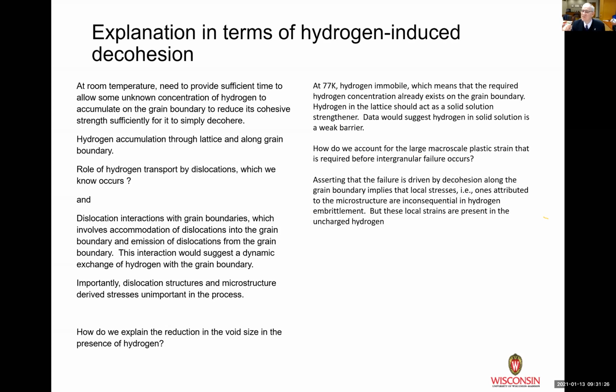The other thing I said is that it's very, very important for you to say, let me look at all of the results that are available and see if my mechanism holds up. So one of the things I showed you earlier was that at 77 Kelvin, you get a significant reduction in the ductility. You get a change in failure mode. Now, if we're really working at 77 Kelvin, we know that hydrogen is going to be trapped in the lattice. It's not going to go to the dislocations. It's going to act as a solid solution strengthening agent.